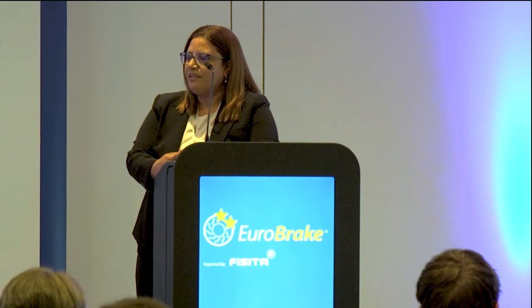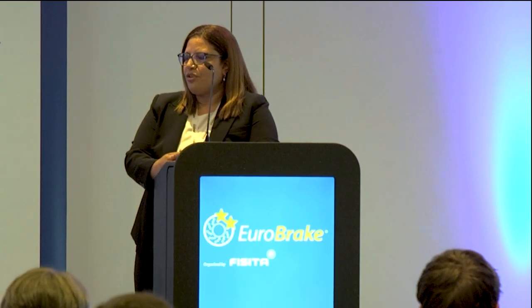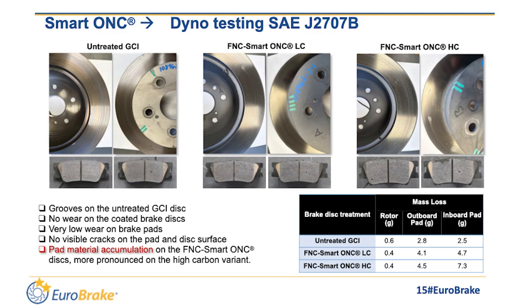The comparison of the different discs after dyno test shows that there is appearance of grooves on the untreated gray cast iron, while for Smart ONC variants, there were no grooves, no wear, no cracks that appear on the friction surfaces. And for the pad, there is a little wear and no visible cracks were observed. And on the Smart ONC variants, we have material accumulation on the friction surfaces, especially for the high carbon one.